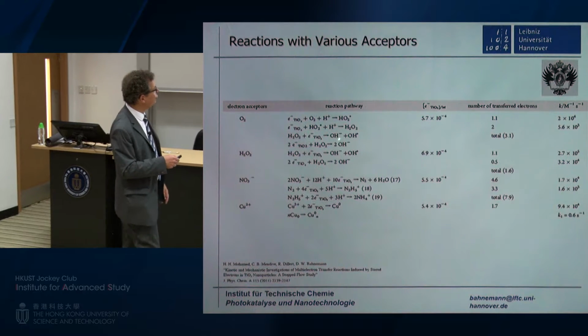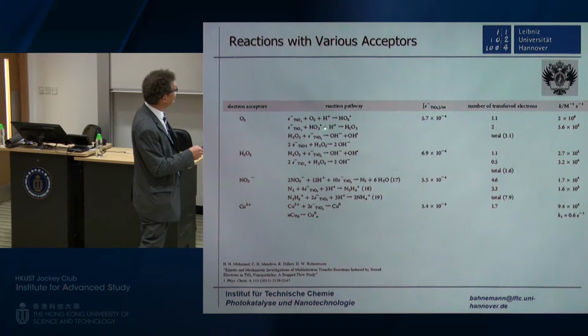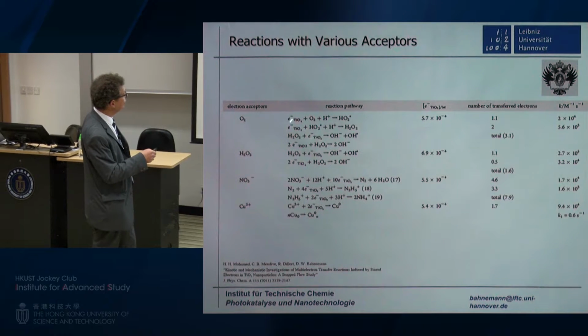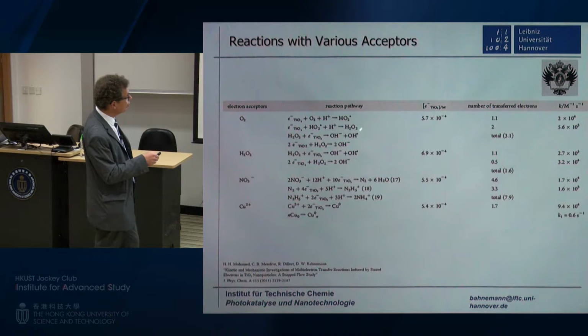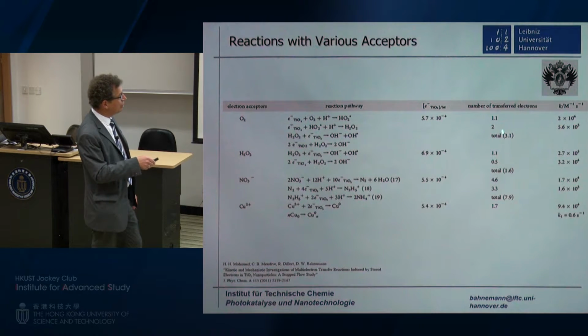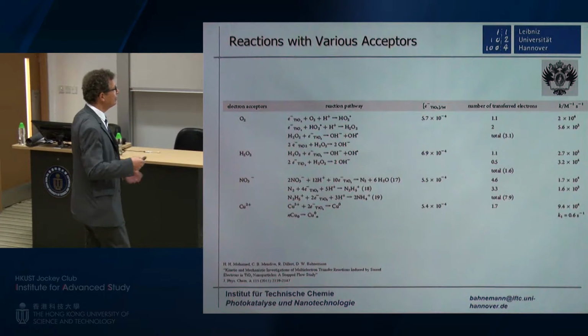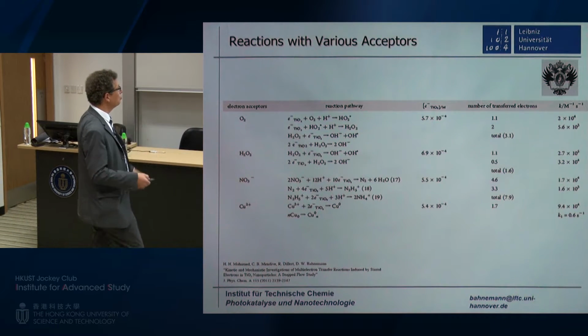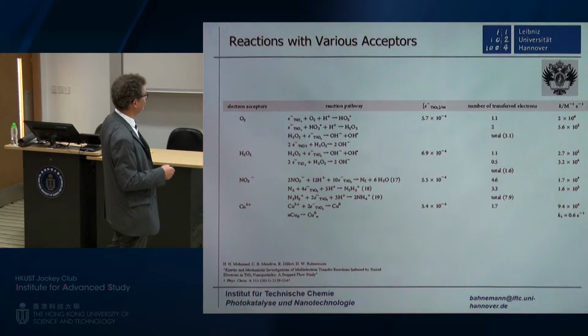If you look more carefully, you can find that the first step that you see is a reaction with molecular oxygen, going to the formation of hydrogen peroxide. Then you get a second step, which is the reaction of the hydrogen peroxide with the electron, and altogether you are utilizing 3 electrons to get from molecular oxygen to OH minus plus an OH radical, which then reacts further to do recombination to get more hydrogen peroxide, for example.